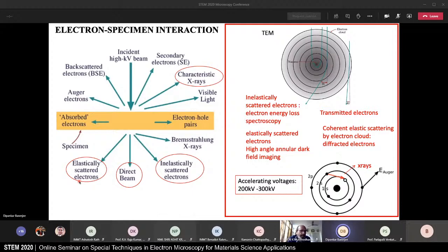We're talking about coherent elastic scattering by an outermost electron cloud, which provides the diffracted electrons. And then we're going to talk about elastically scattered electrons, which allow high-angle annular dark field imaging, and inelastically scattered electrons and their relationship with electron energy loss spectroscopy. The accelerating voltages that we look at in transmission electron microscopy range today from 200 kV to 300 kV in most cases.